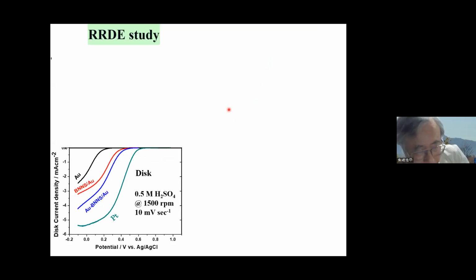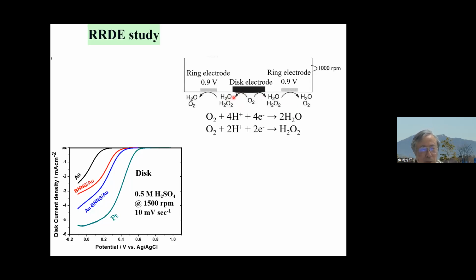Another way to directly detect the fraction of hydrogen peroxide formation in oxygen reduction is the rotating ring disk electrode study. Usually for the oxygen reduction reaction, we rotate the electrodes so that the oxygen supply can be controlled. Then we have a ring electrode surrounding the disk electrode, keeping the potential at 0.9 volt, where hydrogen peroxide can be oxidized. So if oxygen is reduced to hydrogen peroxide at the disk, then the hydrogen peroxide is oxidized at the ring.